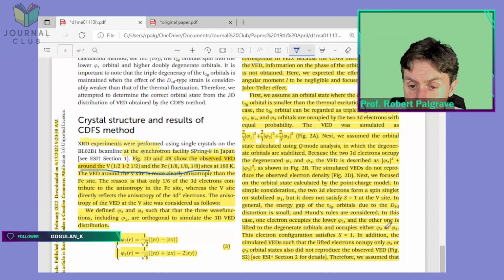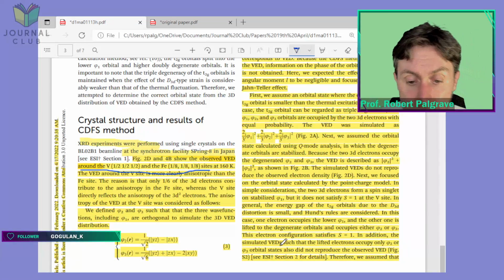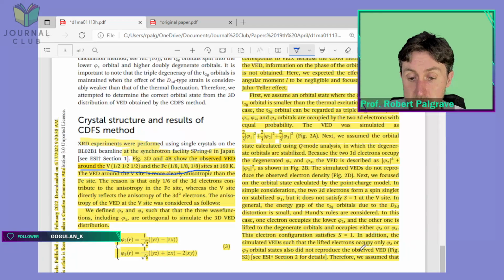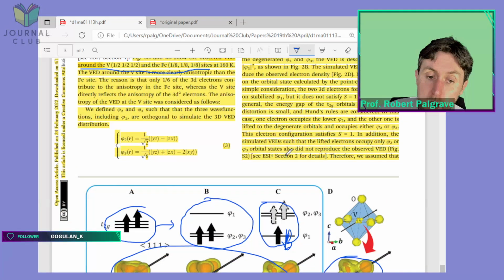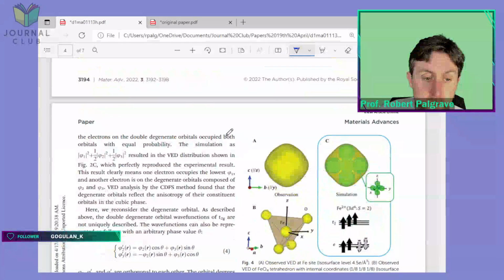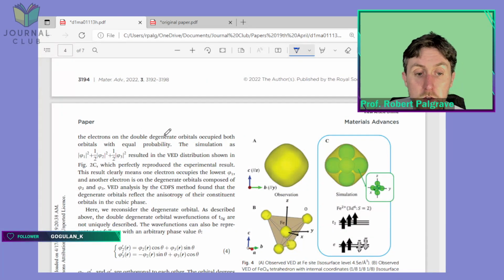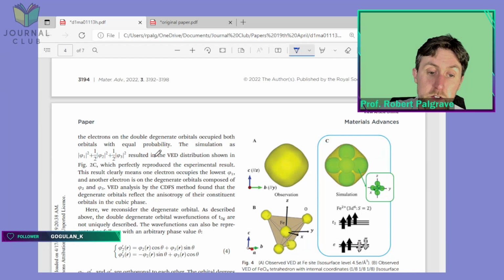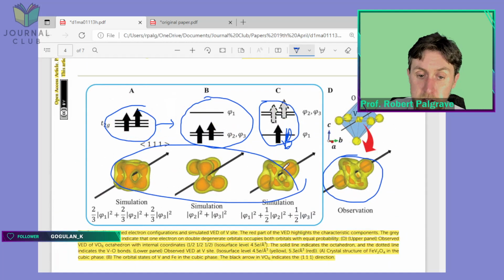The other one is lifted to degenerate orbitals and occupies either Psi1 or Psi2 or Psi3. The electron configuration satisfies the total spin. In addition, the simulated valence electron density such that the lifted electrons occupy only Psi2 or Psi3 orbitals did not reproduce the observed valence electron density, figure S2. We'll have to look in the SI for that, which I haven't got to hand at the moment. Therefore, we assume that the electrons in the doubly degenerate orbitals occupy both orbitals with equal probability. The simulation resulted in the valence electron density shown in figure 2c, which perfectly reproduced the experimental results. So this guy here looks pretty much exactly the same as this guy here. So what they've assumed here, let me rub out this.